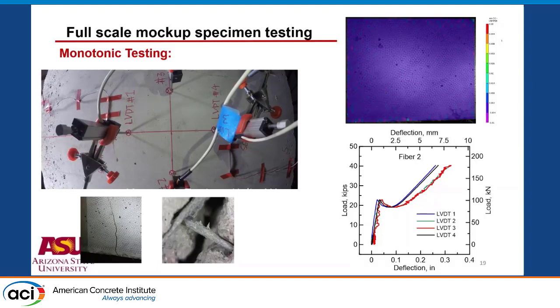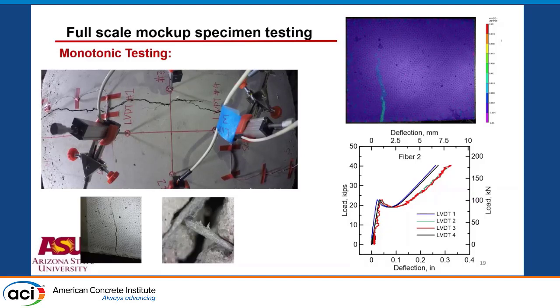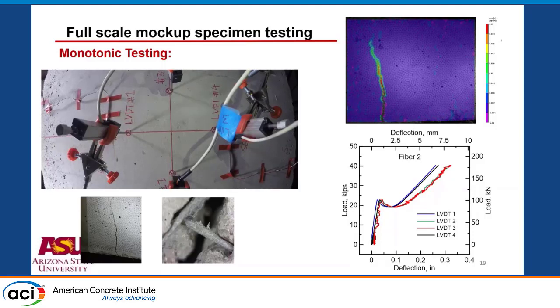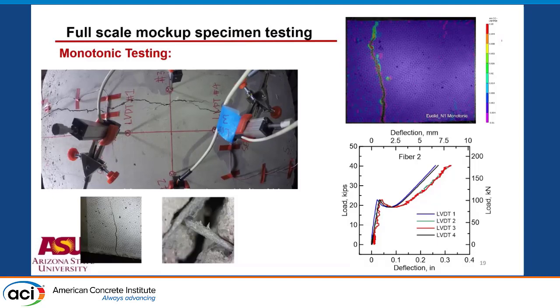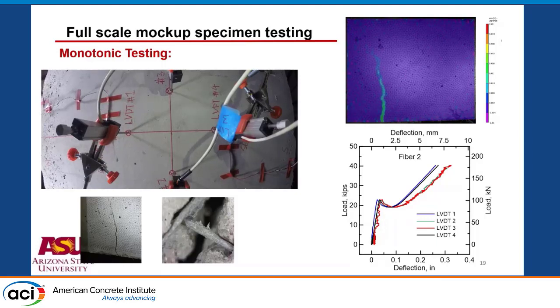So the results that we see here, at least from comparison of 4 LVDTs, four instruments underneath the sample, almost measure the same response. The load is increased, the sample is cracked, the load tries to drop, but the load gets transferred to the fiber. These are samples that have no rebar. Load gets transferred to the fiber.